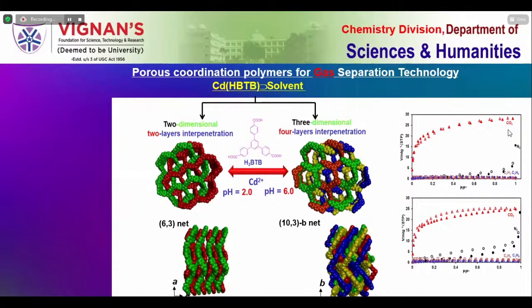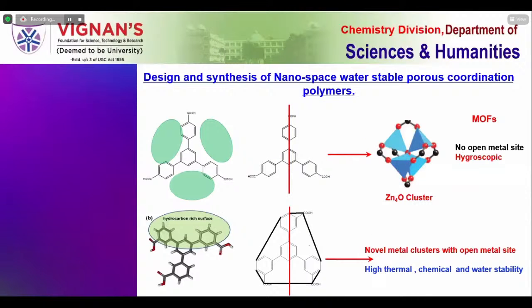Then we thought, why can't we design our own ligand by changing its properties? We looked into the structure of the ligand we used earlier. This is the ligand we used, highly symmetric, with D3h symmetry. We know that highly symmetric compounds tend to be highly hygroscopic. If we reduce the symmetry, maybe we can reduce the water absorption, meaning the water sensitivity can be removed. So what we have done is change the carboxylic groups at the para position to the meta position, so that we reduce the symmetry. Whenever this ligand reacts with metal centers, what we expect is that it cannot react with water, or in other words, that it has a hydrophobic nature.